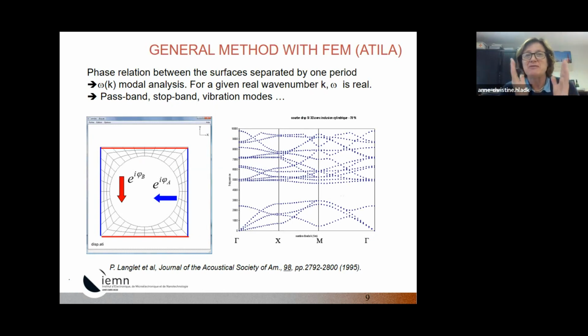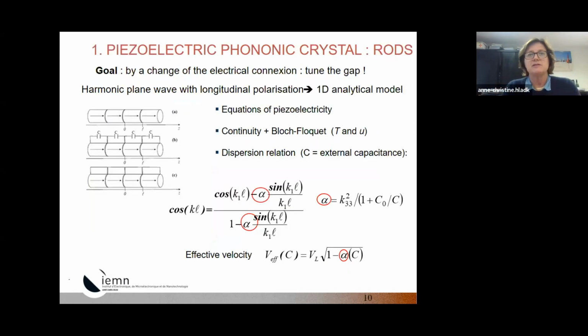So the idea is to develop a general model to get the dispersion curve, and the mesh is based on the finite element method using the Attila code. We mesh only one unit cell. We apply the phase relations on the surface, and then for a given k value, wave number value, you do a modal analysis and you get the eigenfrequencies, and then by changing the wave number, you draw the dispersion curves. So first, the example is about the rods.